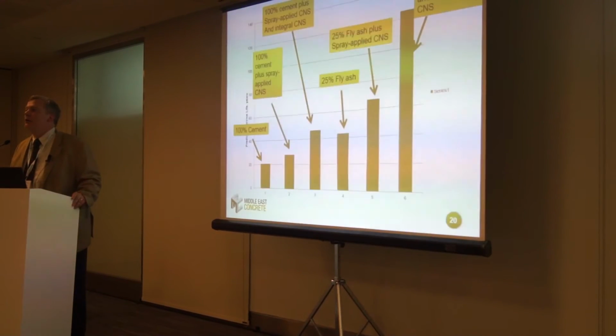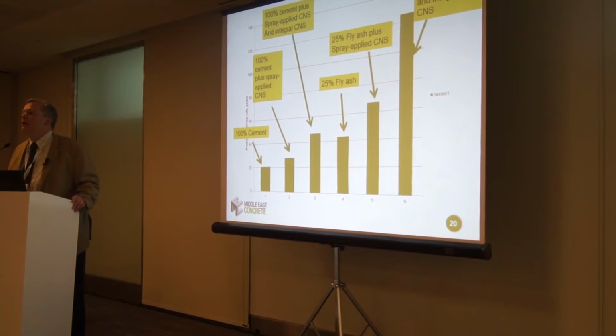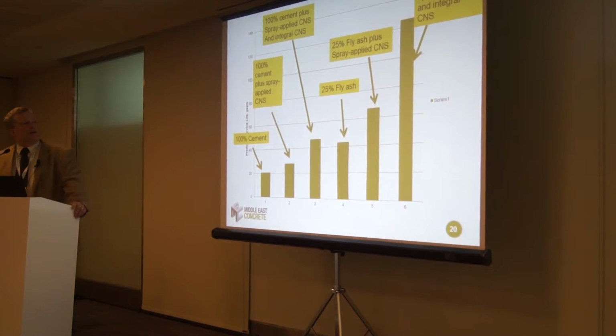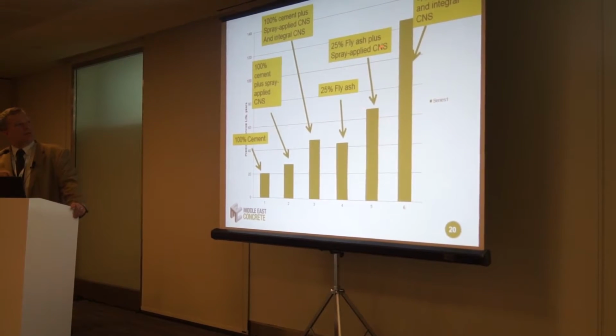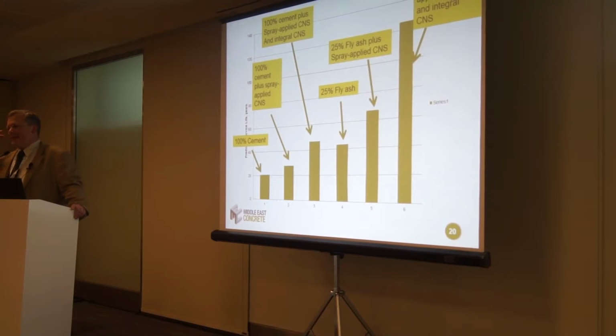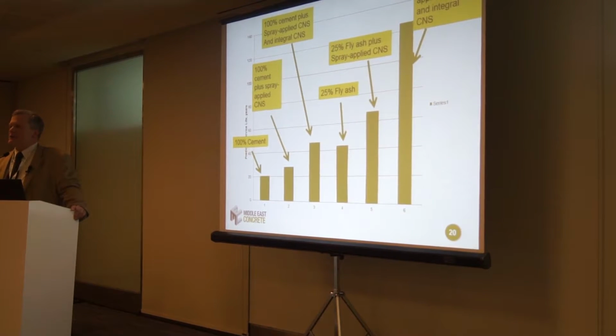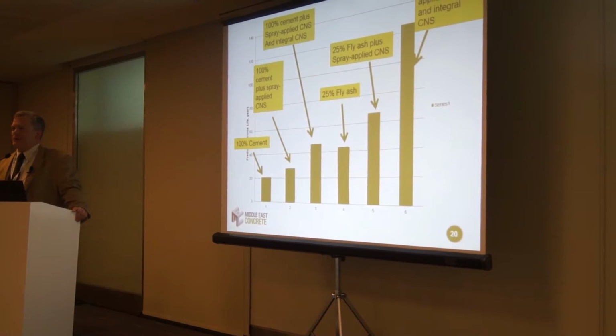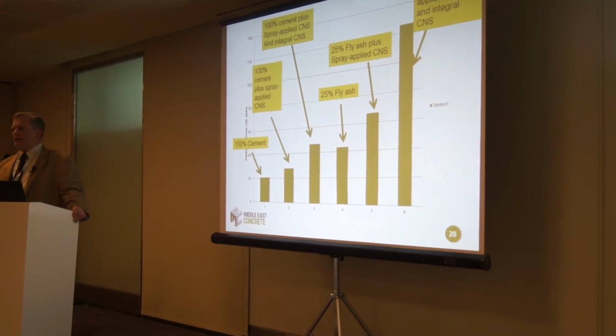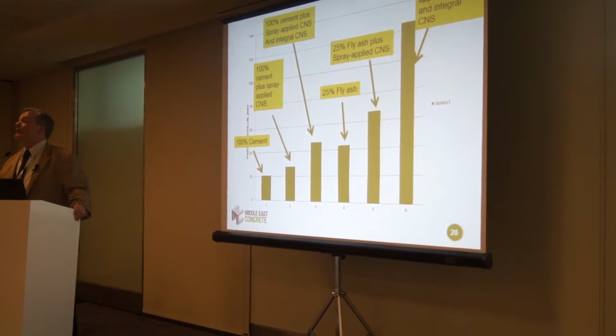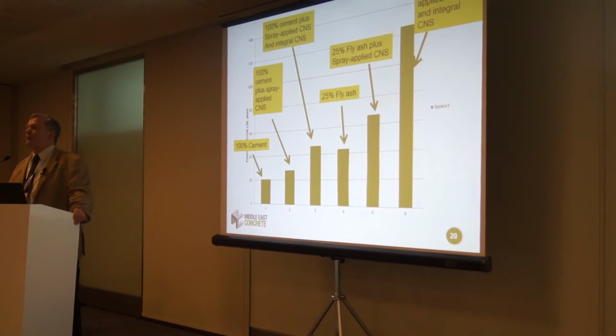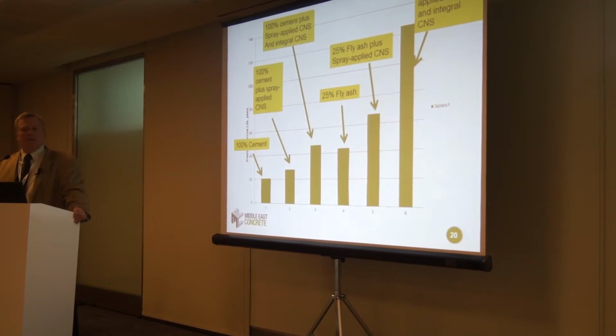Yes, sir? About the integral CNS, what's the percentage we talk about in the assumptions? The integral was a liquid admixture, done at about, I'm thinking in US units, about 1.2%. Now the spray applied is a little difficult to assign a percentage because you're spraying it and it depends on the porosity. In a future study, I would like to weigh the samples before and after, and then I would have an idea of how much it absorbed. But for this study, I did not do that.